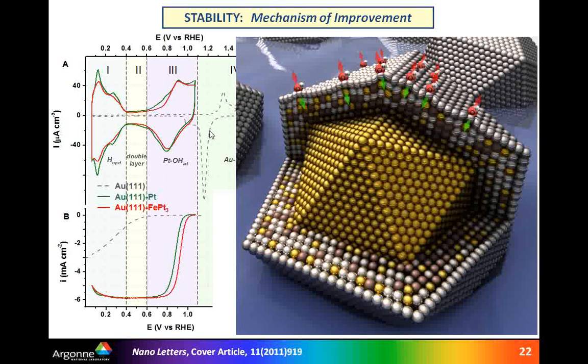So, in other words, there is a substantial difference in oxophilicity, or actually affinity to adsorb oxygenated species, and that is coming from the fact of different fundamental properties of gold and platinum. One can even say that gold is more noble because it's more resistant to oxidation, it's more difficult to oxidize. And in this particular case, gold, which sits inside of particle, stays over there. But huge difference in surface energy between gold and platinum provides tendency of gold atoms to constantly approach a surface of the particle. However, in an electrochemical environment, that never happens because platinum surface is somehow stabilized by those surface oxides.